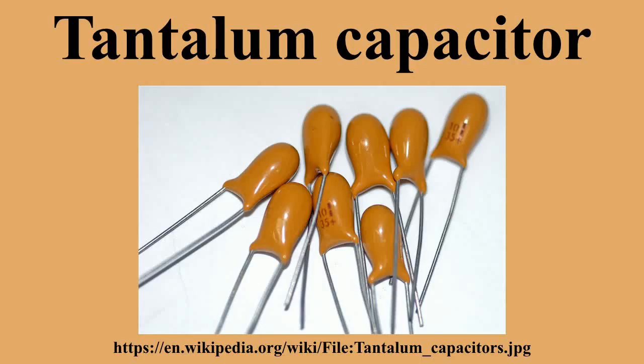Wet tantalum capacitors. The main feature of modern non-solid tantalum electrolytic capacitors is their energy density compared with that of solid tantalum and wet aluminum electrolytic capacitors within the same temperature range. Due to the self-healing properties, the dielectric thickness can be formed with much lower safety margins and consequently with much thinner dielectric than for solid types, resulting in a higher CV value per volume unit. Additionally, wet tantalum capacitors are able to operate at voltages in excess of 100 volts up to 630 volts, have a relatively low ESR, and have the lowest leakage current of all electrolytic capacitors.